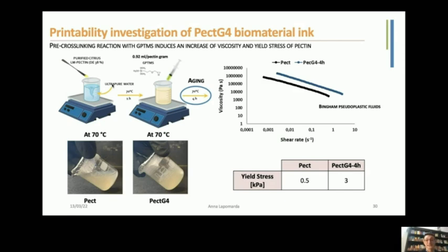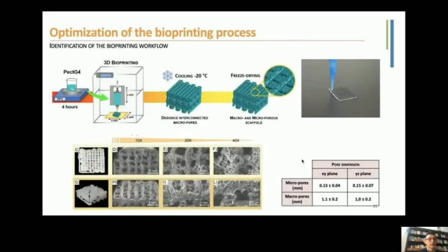and the printability of these materials, analyzing the yield stress. So we can see that normally when it is just pure, it presents 0.5 kilopascal, and instead increasing the quantity of added GPTMS, this increased. What does this result mean? That we are able to produce a gel that, when extruded, can preserve the extruded form of the scaffold. So the other approach was, we created our solution, we extruded the scaffold, we cooled it at minus 20 degrees Celsius, and we induced a freeze-drying process.